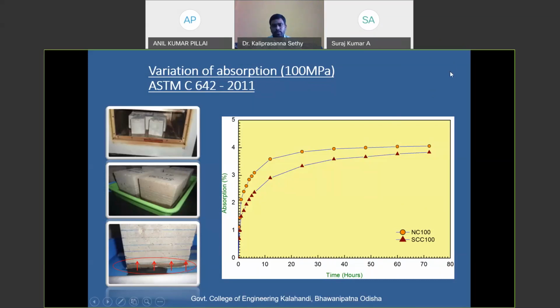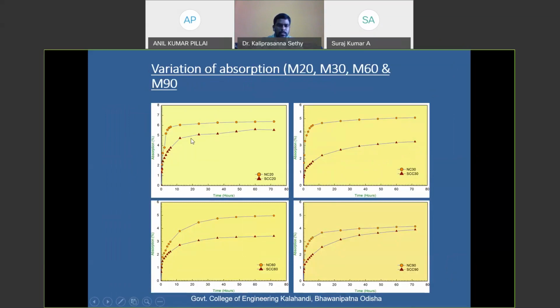Up to 72 hours we have taken the readings, and we observed the trend curves like this. The maximum percentage we found is 4 for M100, and for other concretes it is also showing a very low absorption value. You can see the maximum value is 6 for normal concrete, and for self compacting concrete it is less than normal concrete.